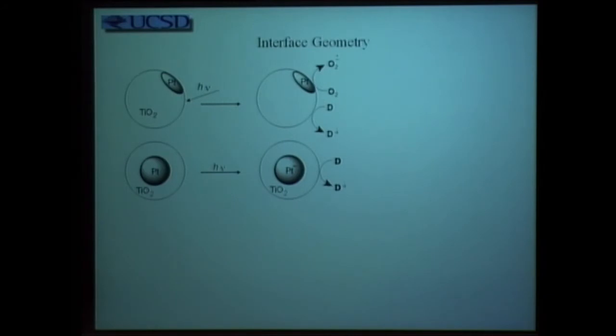What would happen, though, if you simply inverted the place of platinum and TiO2? Well, what you'd find is that now there is no reactivity. That's because the platinum on the outside resists formation of an excited state, and even though these particles would be isomeric to the ones on the second line, the activity will be blocked, showing once again that it's the surface properties in conjunction with an absorbed photon which makes all the difference in photoelectric chemistry.